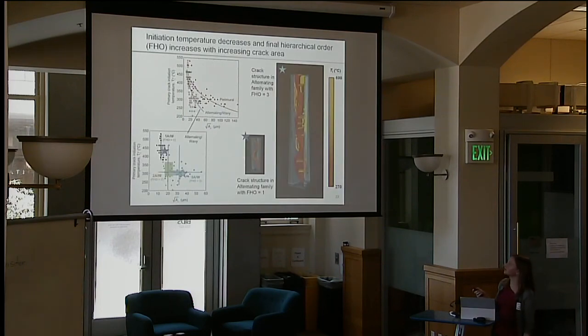Our other finding has to do with the final crack structure after the completion of pyrolysis. So what we've defined is this final hierarchical order, which depends on the number of different crack types in that region after the completion of pyrolysis. So this one, which is a fairly large crack, has several other semi-peripheral and interfacial cracks. So this has a FHO of 3, whereas these much smaller regions tend to have a lower final hierarchical order with just this one wavy crack.